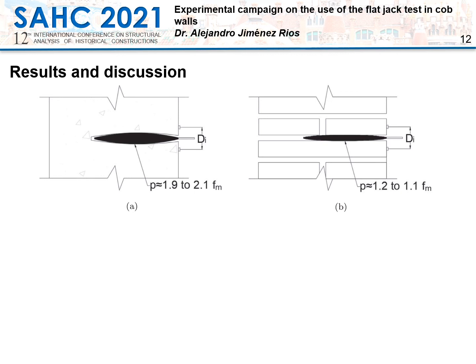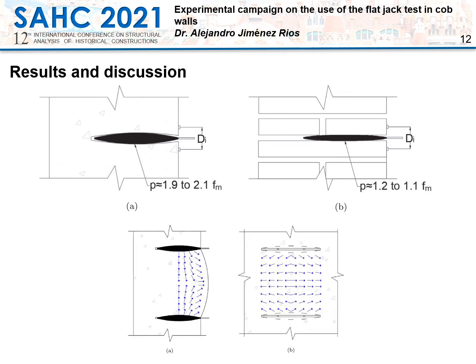As pressure was applied vertically to the material between the flat jacks, it was expected to see larger vertical strains caused by the actual compression of the material than horizontal strains caused mainly by lateral deformation of the material due to Poisson's effect. Nevertheless, after apparently reaching the yielding point, the increments of horizontal strains were relatively larger in comparison to the increments of vertical strains. This phenomenon may be better understood if the relatively high stiffness of the flat jacks in comparison with that of cob is taken into account.